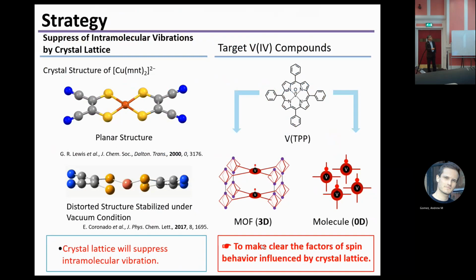You know, in the crystal structure of [Cu(mnt)2]2-, the structure is planar. However, in the vacuum condition, it is distorted. So a crystal lattice which suppresses the intramolecular vibration keeps it planar. So the lattice is very important. Then I focus on the oxyvanadium TPP. The starting material is zero dimensional, a soft lattice. We put this oxyvanadium into the MOF, a strong, rigid lattice. We compare the soft lattice and the three-dimensional strong lattice to make clear the factors of spin behavior influenced by the crystal lattice.